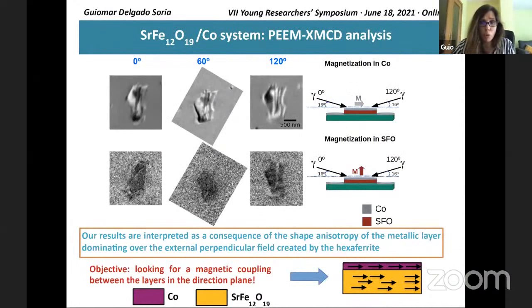Then we grew a cobalt overlayer by molecular beam epitaxy. I think this slide is really interesting, because we can see the different magnetic domains in the cobalt layer and in the iron. On top corresponds to the cobalt layer. We took different XMCD images with a big magnetic contrast range in the cobalt layer, and comparing the images from 0 to 120, we can see that the domains change the contrast a little. When a white region appears, you can see black, which means we have magnetization within the plane.